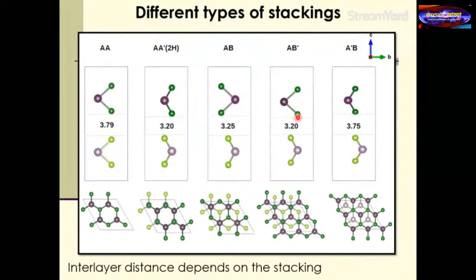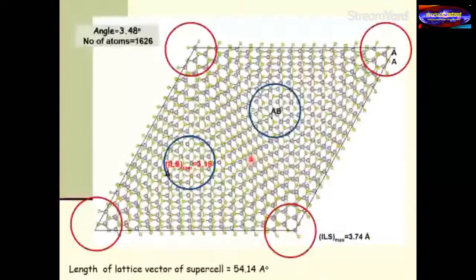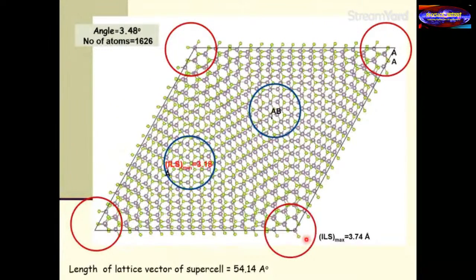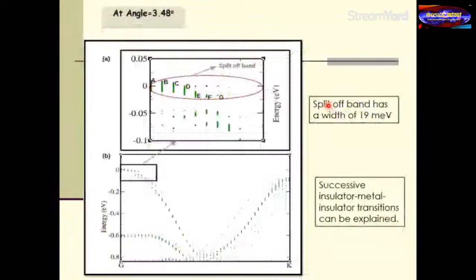So when we looked at these structures, within our calculations we can move to the minimum energy configuration. We find that over here the separation between the layers, measured as the separation of the outermost atoms in each layer, came out to be 3.74 angstroms, whereas it came out to be about 3.2 angstroms over here. So essentially, this was one difference which we found. And then again, we did the same analysis which I've been talking about. Okay, and what do we see? There's something different.